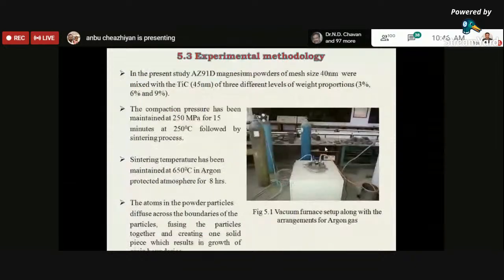So this is the experimental methodology that we followed. We used a vacuum furnace setup along with argon, which gives an inert atmosphere. When magnesium interacts with oxygen, it forms oxide, which we can't use further, so magnesium has to be synthesized only in an inert atmosphere. In the present study, we have not used pure magnesium. We have used AZ91 magnesium alloy powder, a die casting material containing 9% aluminum and 1% zinc. The powder size is taken as 40 nanometers and the titanium carbide as 45 nanometers, available from Sigma Aldrich.